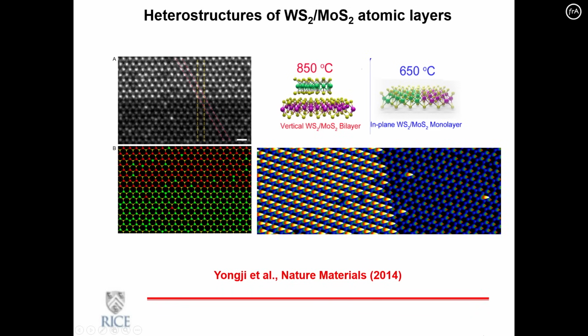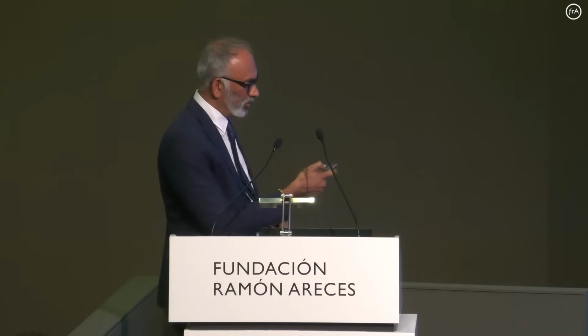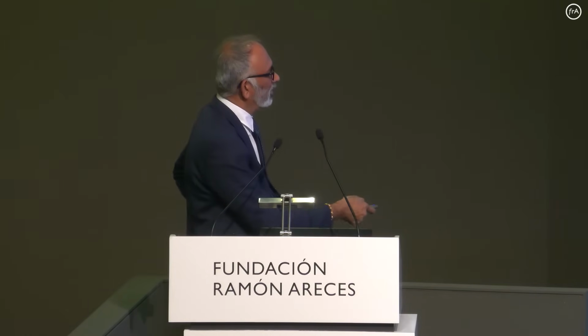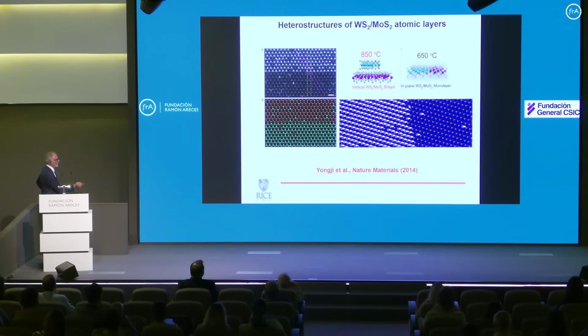You have two different compositions, and this is not boron nitride and carbon. This is a different composition, different materials. For example, very similar: one is tungsten sulfide, the other is molybdenum sulfide, and both are, again, 2D layered systems, but both have different properties because one is tungsten, one is molybdenum. They have a similar structure so that you can actually stitch them together. So you can essentially make structures like this where you have an atomically sharp interface. On one side, you have tungsten sulfide. On the other side, you have molybdenum sulfide.